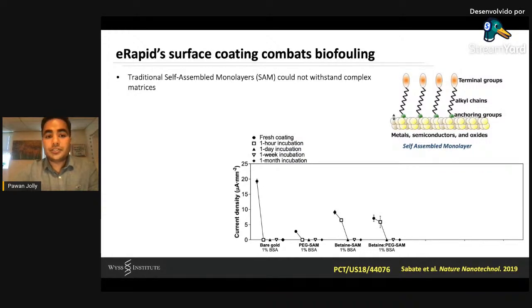If you actually look into traditional self-assembled monolayers and you coat the self-assembled monolayers on bare gold, what you see on the graph is you actually lose more than 40 to 50% of the conductivity of the metal just because of the insulating nature of the self-assembled monolayer. And these are the most commonly used PEG SAM or betaine-based SAM because of their anti-fouling properties. So when you challenge these sensors in, let's say, 1% BSA for 1 hour or more, you lose nearly all the sensitivity within 24 hours.